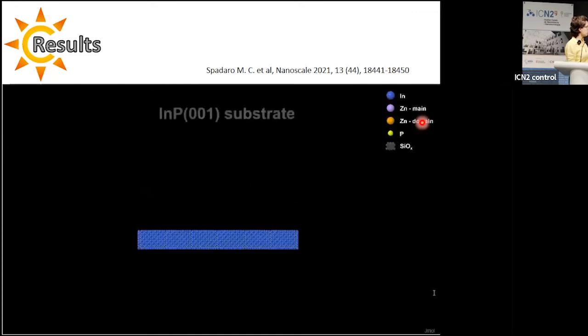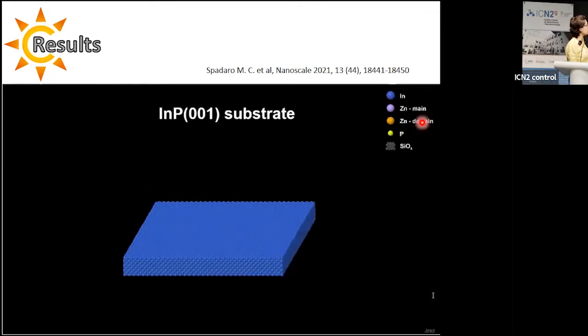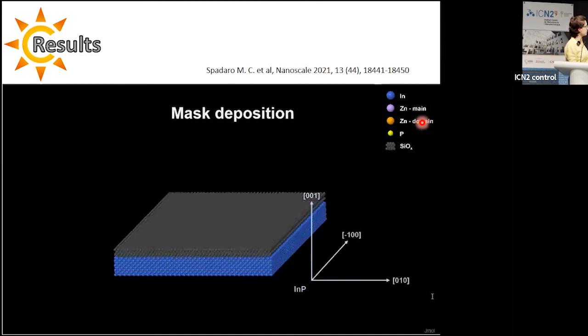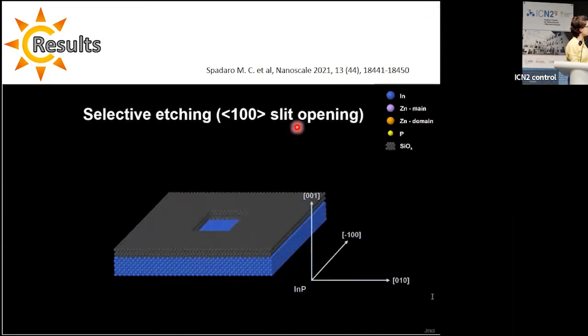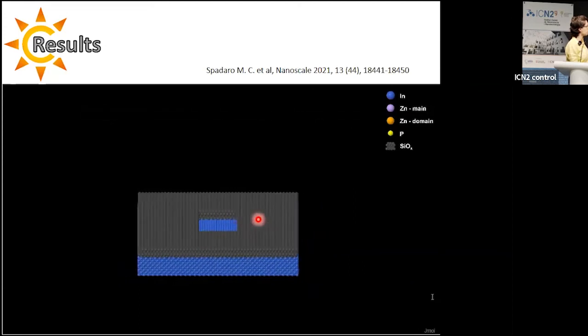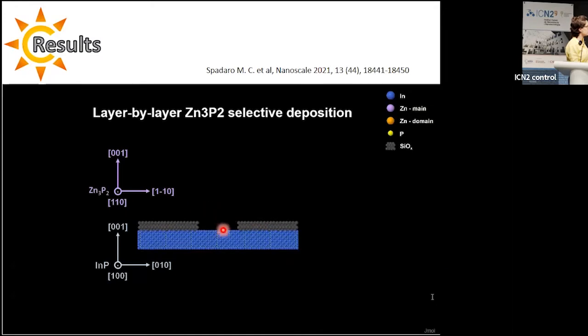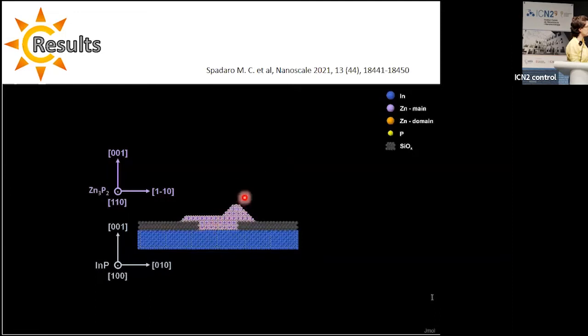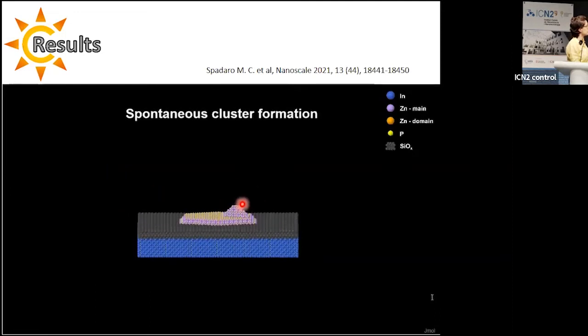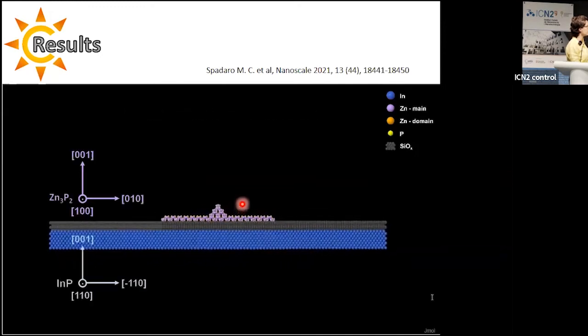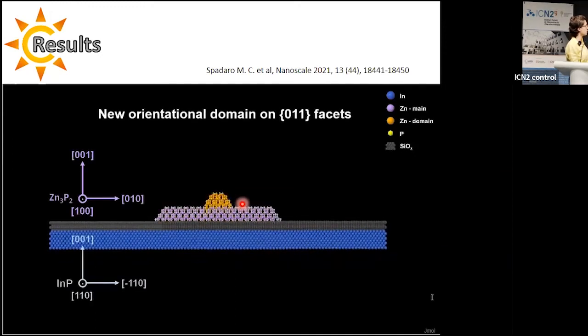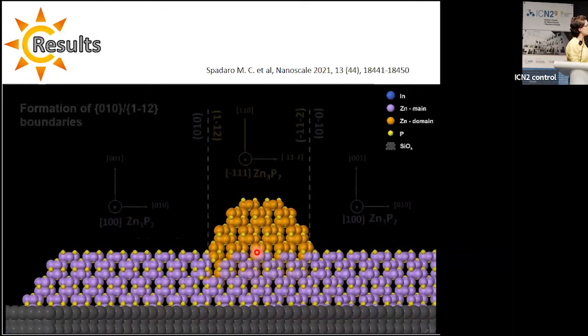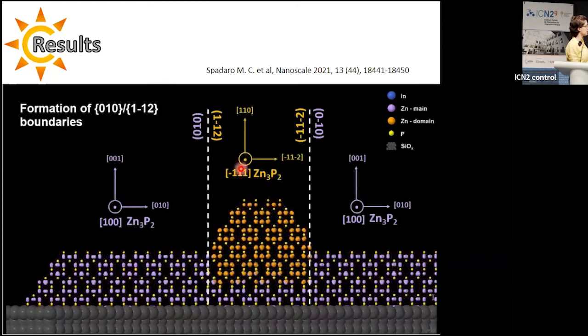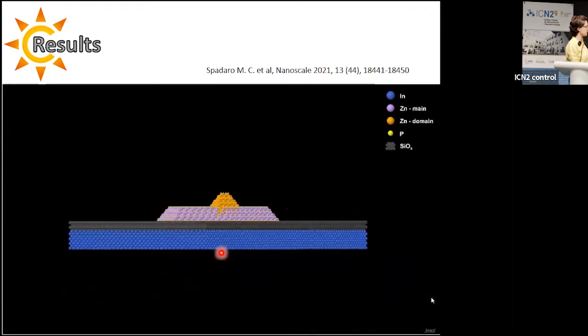In order to understand the formation of this type of domain, we created this 3D atomic model where we have the indium phosphide 001 substrate, where we deposit on top the mask, and thanks to lithography, we create this type of aperture. Then that is where the material starts to grow, depositing. At the early stage, we already observed the formation of a cluster of these seeds that possess specific surface termination, in particular the 101, where on top the material continues growing, but with a different orientation. We can see that the zone axis is the 111, while in the other cases the 100.